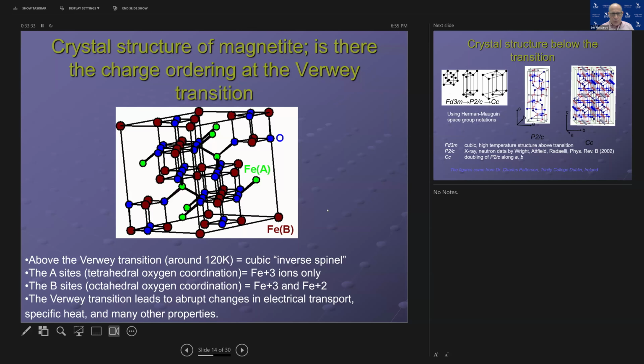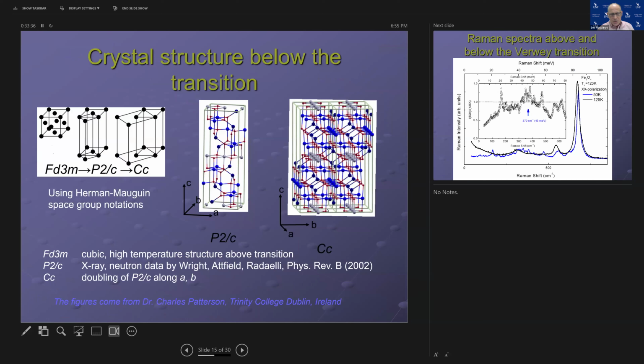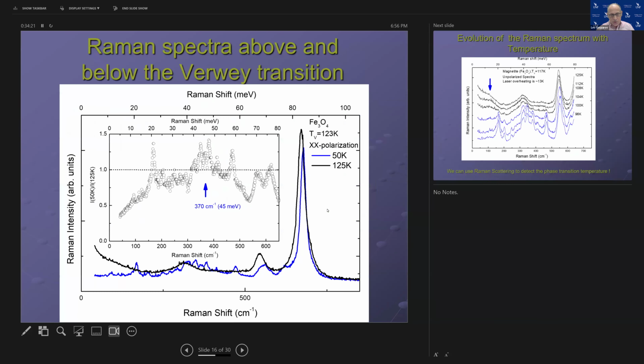Now, if you try to figure out what's happening with the crystal structure of magnetite, you quickly find out that the unit cell, that smallest volume that repeats itself in the material, becomes bigger. At the beginning of the talk, you probably remember that I mentioned that the number of Raman lines that you see in the spectrum depends on the crystal structure. So if you have a bigger unit cell, you expect to see more Raman modes. In other words, you could expect to see the phase transition in the Raman spectrum. And that's pretty much what you see.